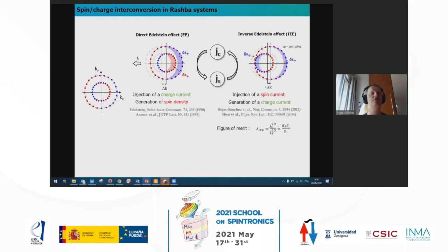So if you have a system with a very large Rashba coefficient, but a very short momentum relaxation time, like metallic interfaces, like silver bismuth, in which this effect was discovered, you may see some effect, but it's not as large as you may expect from the large Rashba coefficient, because in metals, the tau is very short, typically a few tens of femtoseconds maybe.